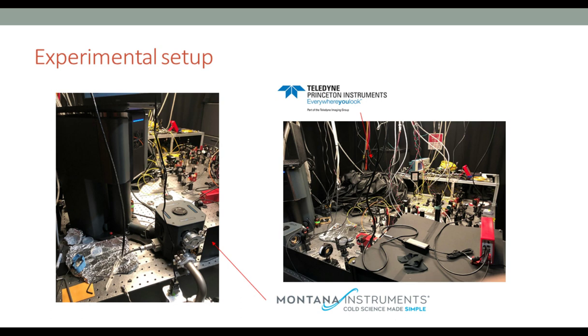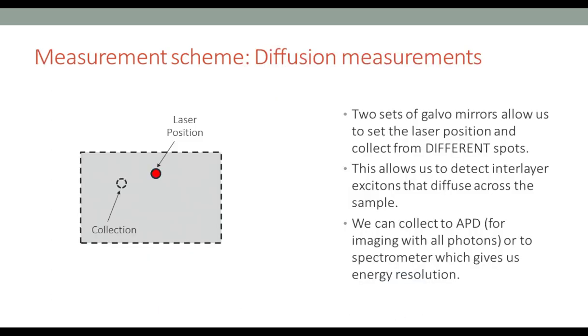I mentioned that we use two different galvos to excite and collect from two different positions. So this is essentially the measurement scheme. We park our laser in a given position by steering one of the mirrors, and then we have a second path that can be collected into either a photodetector or the spectrometer, and we can scan this second collection all across our sample, which allows us to excite and collect from different positions. We can actually measure how much the excitons move across our sample away from the actual excitation position. Unless said otherwise, most of the diffusion measurements are taken this way.